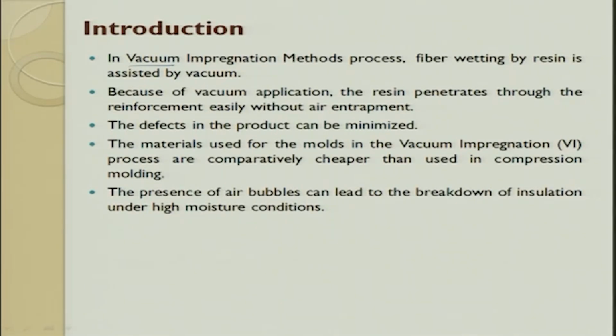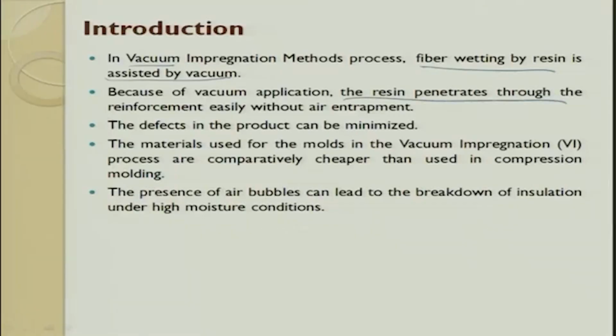So, in the vacuum impregnation method, the fiber is wetted with resin and it is assisted by vacuum. Either you buy it from the market as resin infused, or you buy the reinforcement from the market, a fiber mat, and then you reinforce it. Based on the vacuum application, the resin penetrates through the reinforcement easily without any air trap. One way is you pour and then you try to sweep it through. When you sweep it through, there is still a possibility of having small air bubbles. And what is the problem with these air bubbles?